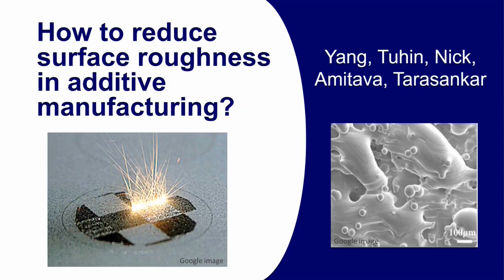Because there are multiple mechanisms at play here, physics-based mechanistic modeling is not as attractive as models based on experimental data. I am going to discuss our recent research on a model-based method of reducing surface roughness that we just published in the Journal of Manufacturing Processes. The model is based on independent experimental data of surface roughness of four alloys. We show that a dimensionless index can predict and reduce surface roughness. And here we explain how to construct this index and how to use it for printing parts with smooth surfaces.